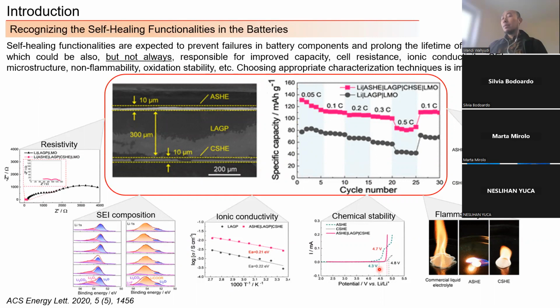Self-healing functionalities that we use in the battery are expected to prevent failures in the battery components, which in turn, we expect will extend the lifetime of the batteries. And also remember that the self-healing functionalities also can improve, but not always, the capacity of the cell, and also can lead to lower cell resistance, or ionic conductivity, chemical stability, or SEI composition, and also flammability.